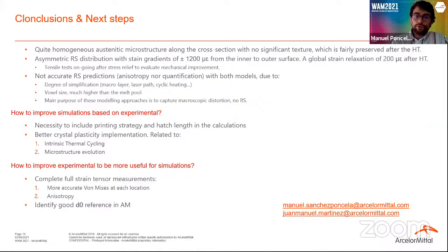Yeah, so what I pretend to say is that in reality the scanning strategy is not accounted for when solving the residual stresses. It is not used in the mechanical simulation. It is incorporated in a micro high fidelity model, where only a few paths are done to solve the thermal behavior of each layer, which is then extrapolated to a macro layer. But those are commercial softwares, and we don't have access to the details on how they do this micro high fidelity simulation, I insist, for the thermal behavior. Then for the mechanical behavior, they don't use it.